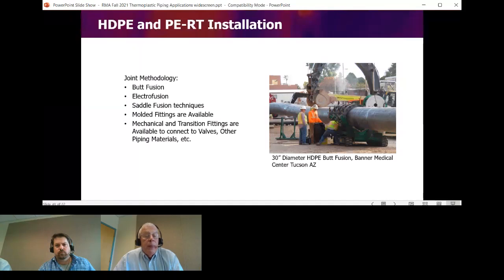Mechanical joints are available, as we saw in the previous picture, which can be connected to your standard gate valves, air valves, expansion joints, or whatever you need, and they are available in both slip-on and restrained style joints. One thing you need to pay attention to is when you're using mechanical joints, sometimes the HDPE tends to creep over time. So when you look at a selected fitting, some recommend a stiffener underneath to prevent that creep over time and loosening of the MJ style joint.